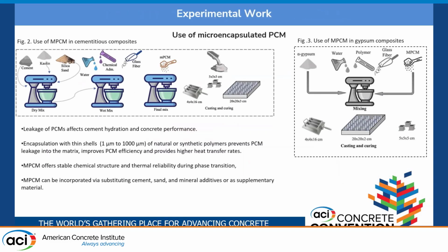So in our research group, we have mainly focused on the use of microencapsulated phase change materials and shape-stabilized phase change materials. The idea of using these materials, first of all, is that while we're microencapsulating them, we prevent the leakage of phase change materials, and we try to reduce the effect of PCM on our matrix, and not affect the concrete performance. And it also provides higher heat transfer rates, and they're actually very thermally reliable compared to the direct incorporation methods.